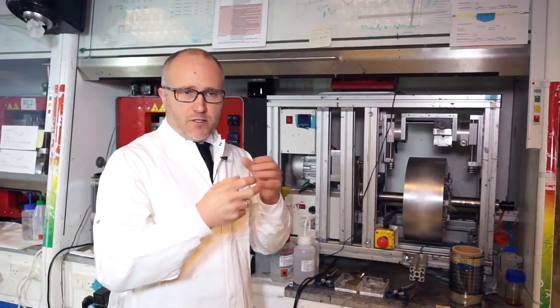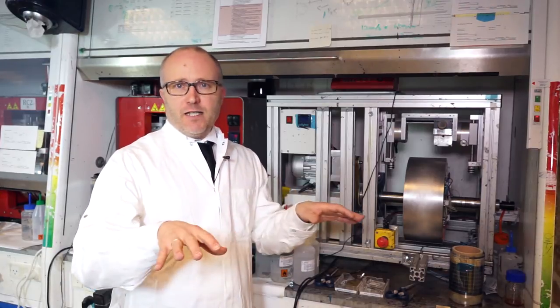This is in stark contrast to spin coating, where static fields are not so critical because you have a very large shear field due to the rotational action of the spin coater. So if there is any static charging effect that has a tendency to push your liquid ink around and change your film thickness, the shear field evens this out.